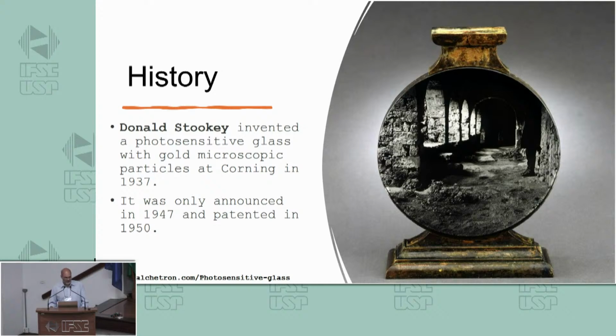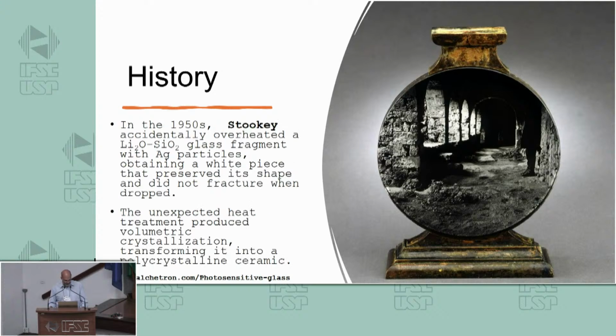In the beginning, it was in the system sodium oxide, silicon oxide, and to improve the chemical resistance of this glass, he changed it to the lithium silicate system with silver nanoparticles to get a better chemical resistance. So this was the glass that he forgot in the furnace, and the next day, he was frightened when he found the furnace at 900 Celsius degrees, much higher than the temperature he had planned.